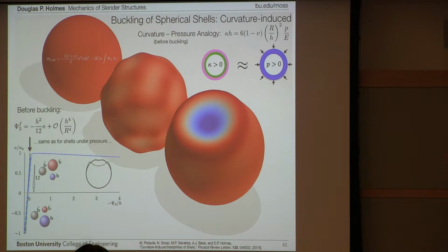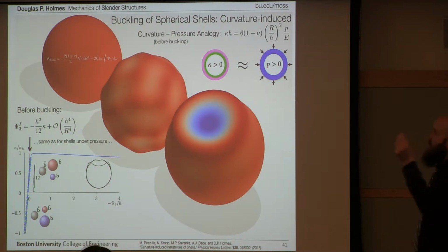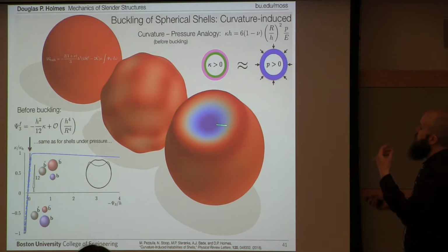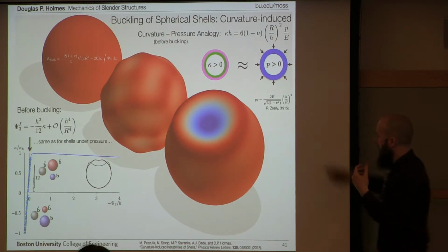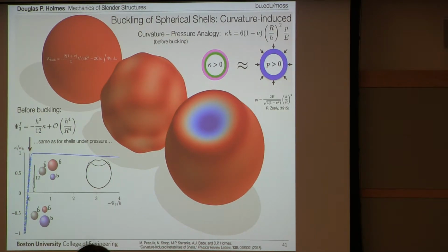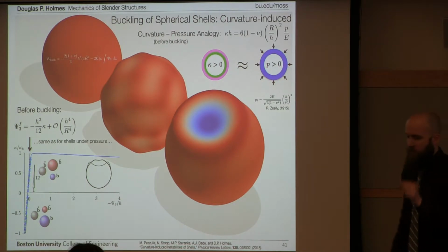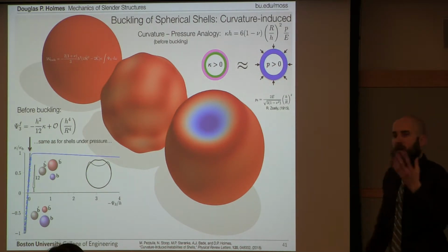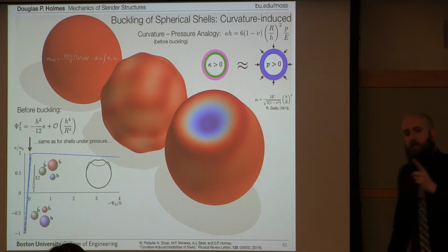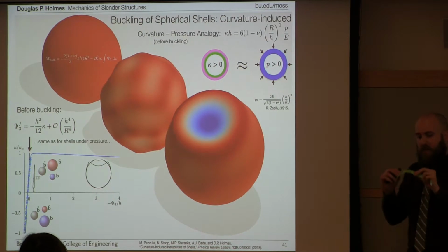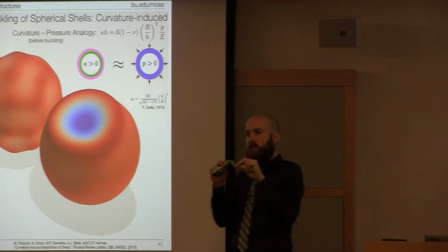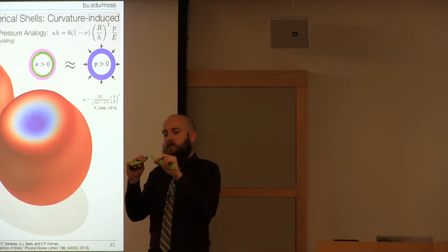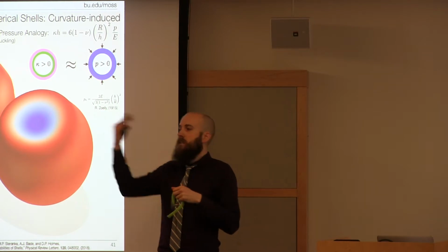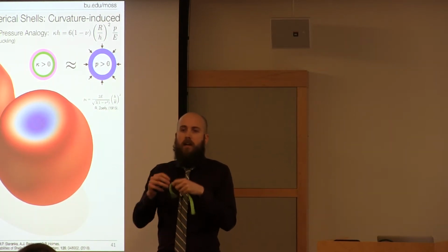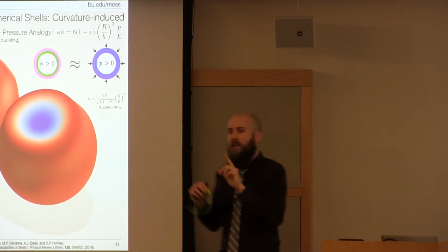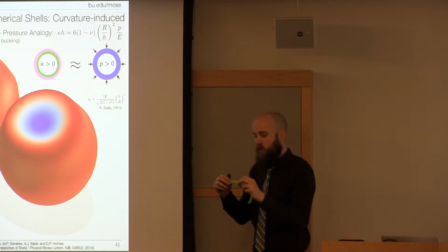However, and this is a kind of an important moment, this would tell you that I can just use the pressure buckling case to predict when this thing should buckle under curvature. This is a classical problem that dates back over 100 years ago to when a shell will buckle under pressure. But this is where things can go very wrong. We learned buckling as engineers usually in one framework, which is the Euler buckling of a beam. And this is a very misleading way to learn about buckling, because you make a very important assumption at the beginning, that this structure is incompressible. And then you write down your strain energy, you write down the work being done to it, and you solve this eigenvalue problem to figure out what load will cause this thing to buckle. That's a very misleading way, because that's not actually what tells you when a structure will buckle.